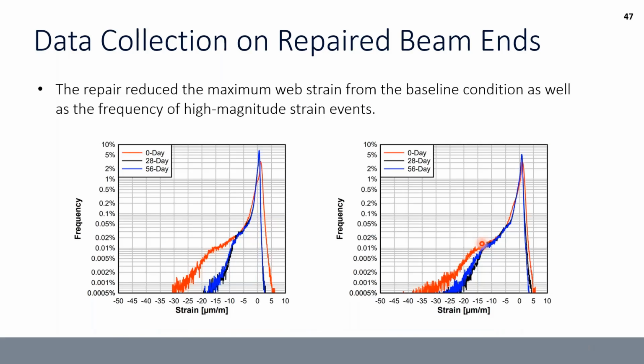A similar trend that we saw on our data collected, here you can see that we're getting smaller strains initially. This is because the level of corrosion in that barren column was not as high as the New Haven job. So where we were looking at over 200 microstrain, here we were starting at a max of about 30. So we did see a drop in the frequency of those high magnitude strain events.